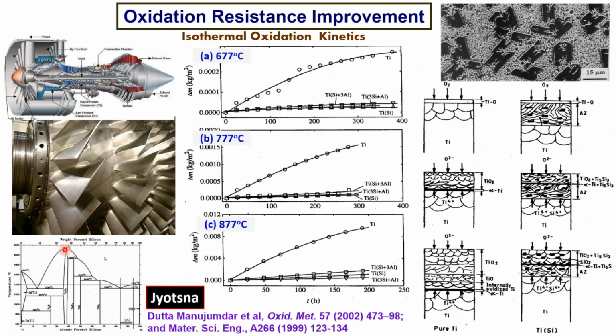Silicide phases, which are congruent, have a very high congruent melting maximum and are very oxidation resistant, so they make up almost 80 to 90% of the entire surface. They cover the surface either as primary phases or as part of the eutectic. As a result, if you compare the oxidation kinetics of pure titanium with the alloyed layers at the bottom, you can see there's a significant difference in the kinetics of oxidation. In other words, these silicide layers are very effective in preventing oxidation of the base metal, which is titanium in this case.